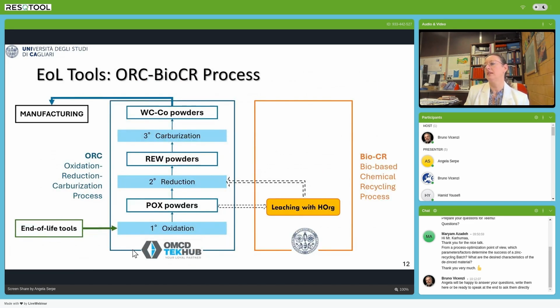So now we can see the application of this kind of approach to real material that can be provided, for example, by a thermal regeneration process that is able to produce tungsten carbide cobalt powders starting from end-of-life tools. In particular, this regeneration process, in our case, is being carried out by the OMCD TekHub through a first oxidation step that provides oxidized powders, then a reduction step that provides reduced powders, and a further carburization step that provides the final WC-Co powders.